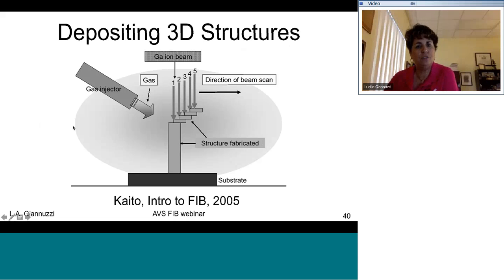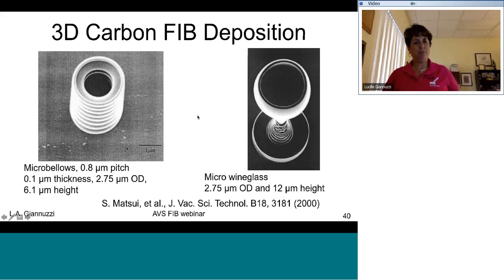All right. You can also deposit 3D structures by basically making a cantilever structure and overlapping the beam slightly with the previous position before it. And with this, you can build up 3D structures. So this is an example of 3D carbon deposition. This is a micro bellows. This is a micro wine glass, and I believe this wine glass was in, or is still in, the Guinness World Book of Records for the smallest wine glass to be used. Later when I have a glass of wine, however, I want a glass that's a bit bigger than this. So.